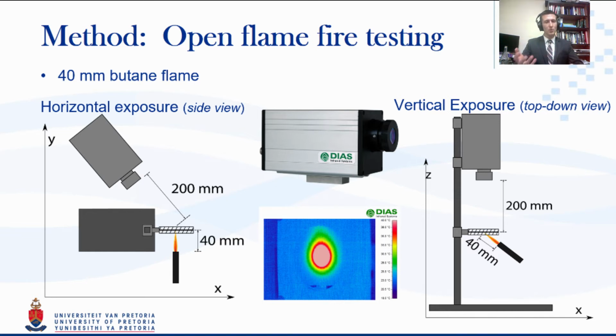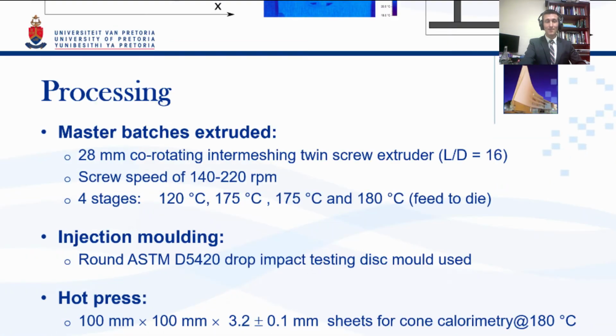But what we also could do in this case is expose the material from the side. And as one sees here in the horizontal exposure, which is from the side, we could actually simulate a material where the flame has started on the floor and is now starting to touch the side of it, so that we can get an indication of whether there is melting, whether there is flow of the media, whether it actually ignites, and a lot of other such interesting results.